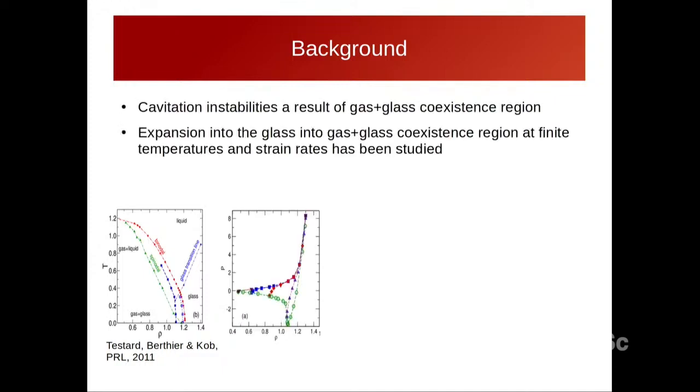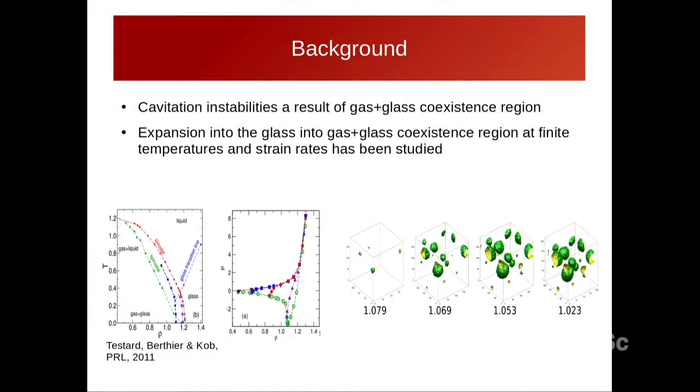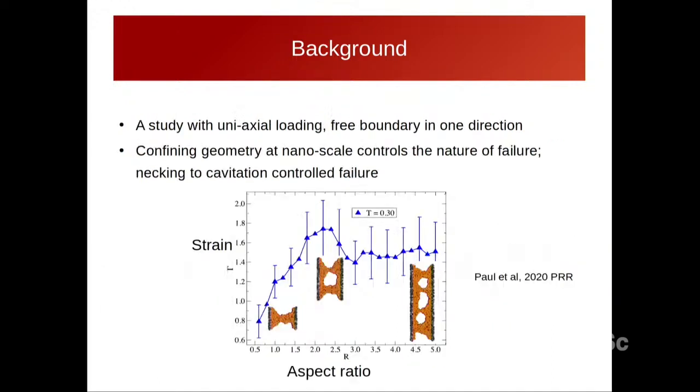This is one of the studies of cavitation in simulations. This is a study by Pinaki. What they have done here is they start from a high density glass, and they expand it into this gas plus glass coexistence region. As they expand it, we see cavities forming in the solid, and this has been done at finite temperatures and finite strain rates. There are some hysteretic effects as well that they have shown here, but these are not very important to what I'm going to talk about, so I'll come to that.